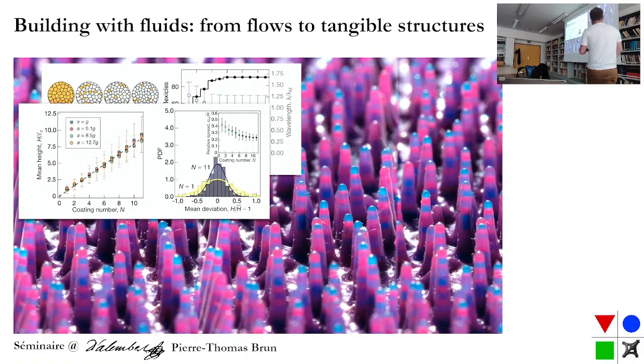Okay, so we were interested in understanding how tall these things were and how different they were from each other. So you can look at the mean height of those things. They grow linearly with the number of coatings, and basically they grow with the capillary length. So every time you're applying a coating, you're adding a little bit of volume, which of course scales with the capillary length. That's not very surprising. But what's a bit more surprising is this.